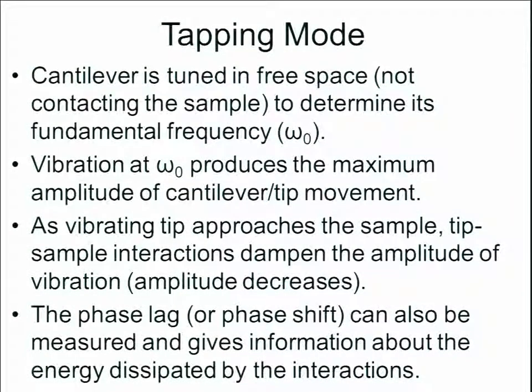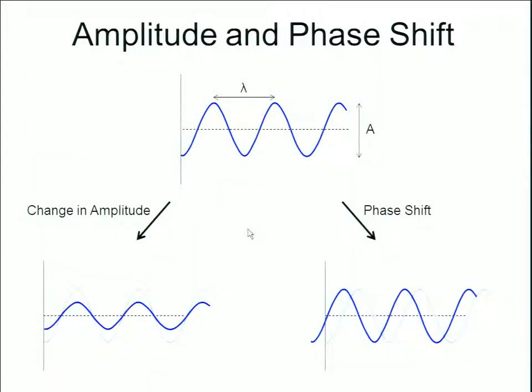As the vibrating tip approaches the sample, the interactions will dampen the amplitude of vibration. There can also be a phase shift or phase lag that can be measured, which provides information about the energy dissipated by that interaction. These are different types of information we can get from the same tool by using a tip with the piezoelectric attachment in this tapping mode configuration.